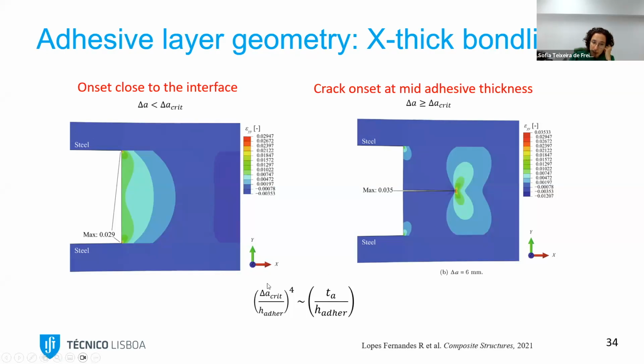And by doing the tests, we found out a geometrical relationship, which depends on the thickness of the adhesive and on the thickness of the adherent. So we can actually control where the crack is going by changing this delta A. So in fact, it's similar to the toilet paper case study, in which we changed the geometry, we perforated the geometry in order to lead the crack path into the place where we want it to go.